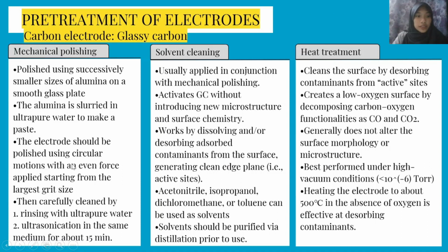And then using circular motions, the electrodes are polished with an even force applied starting from the largest grit size, and then the electrodes are carefully rinsed with pure water, and then followed by ultrasonication in the same medium for about 15 minutes.